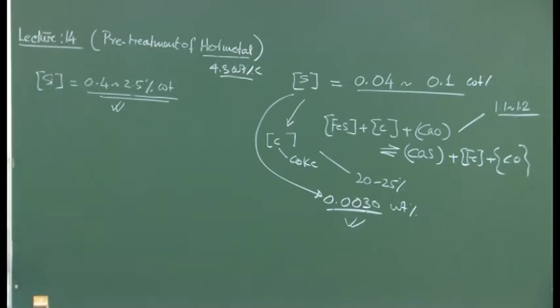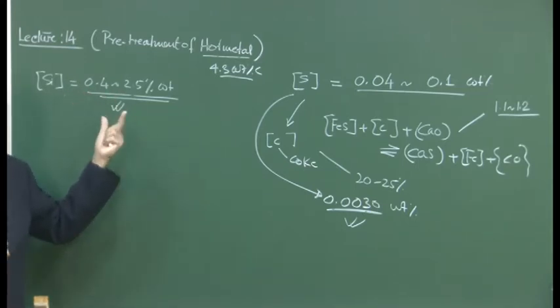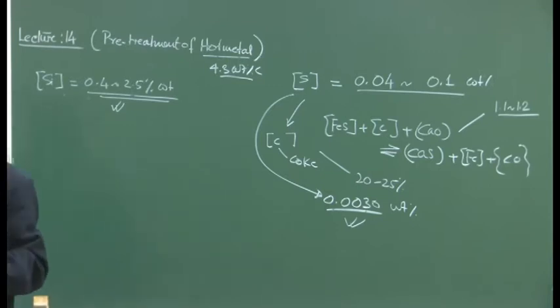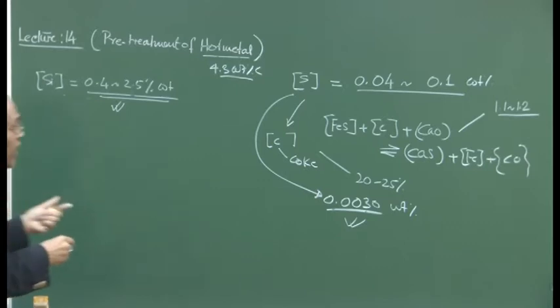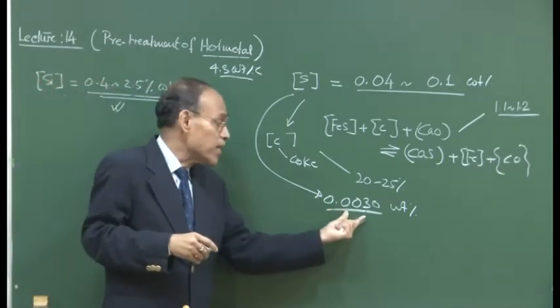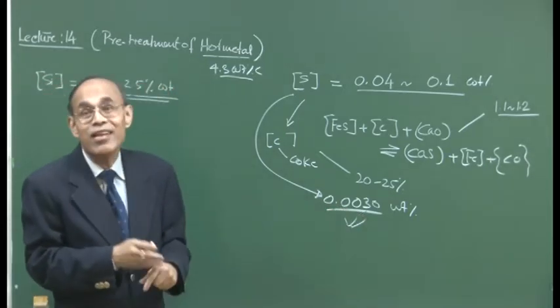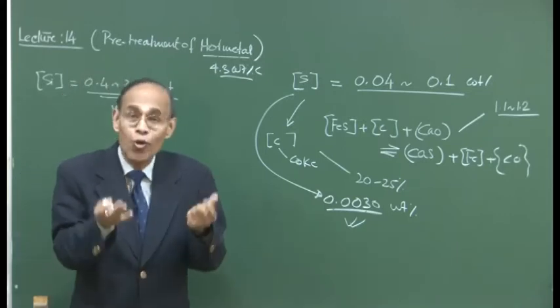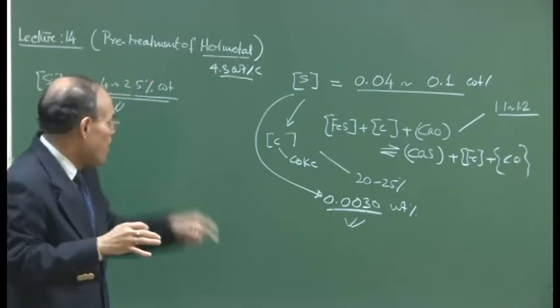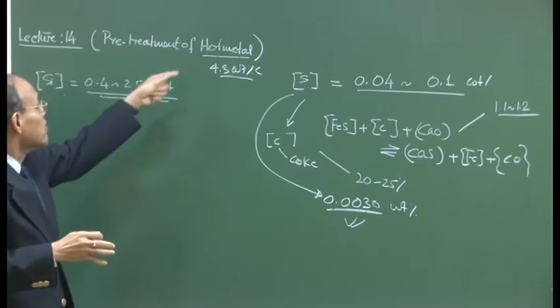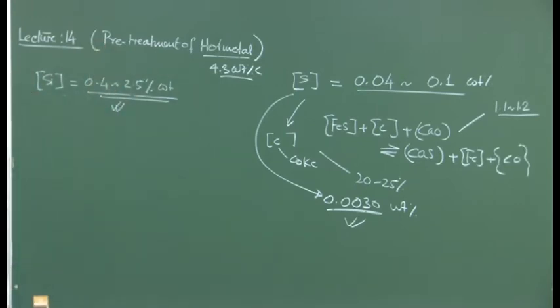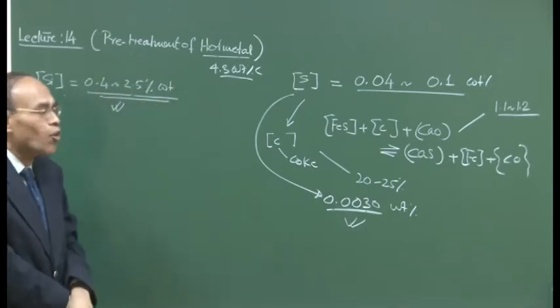What is the advantage of that? If you can reduce silicon content of the hot metal, obviously you will require less amount of lime to be charged in steel making. So, you will save on some money. Similarly, if you reduce sulfur content, you will be able to produce good quality steel which will contain less amount of sulfur. So, an improvement in quality will be there, savings in material will be there, and that you can achieve provided you carry out pretreatment of the hot metal itself.